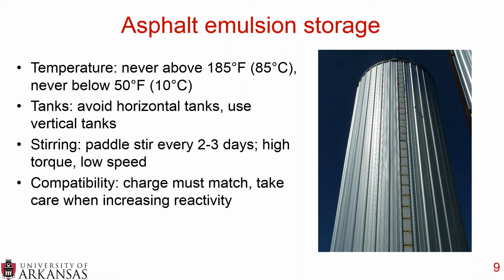Now you can mix reactivities, but you do want to take care if you put a higher reactive emulsion into a tank. So you want to be very careful putting, for example, a CRS into a tank that had CSS, because the CRS is a more sensitive emulsion. It'll break more quickly. You can go the other way with relative ease, but again, you just want to be really careful about mixing different types of asphalt emulsions. Always err on the side of caution before just trying something out for fun, because these are thousands of gallons of asphalt emulsion, and it's a pretty big mess if there's some sort of problem.